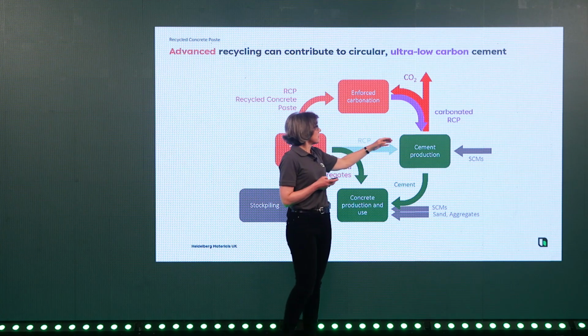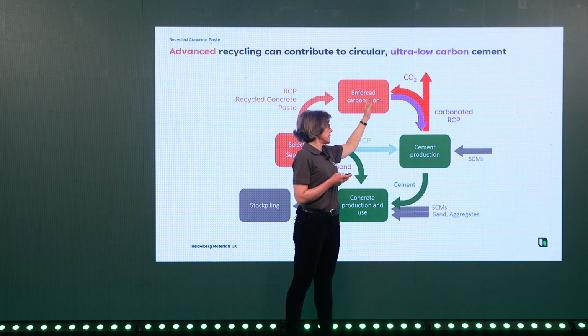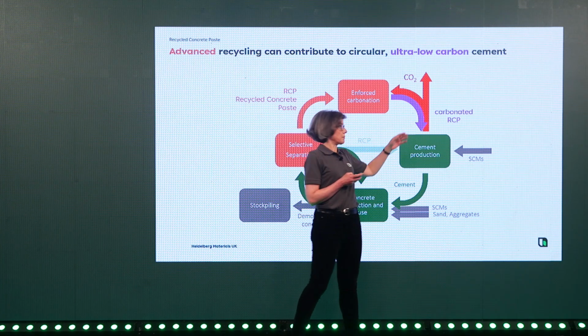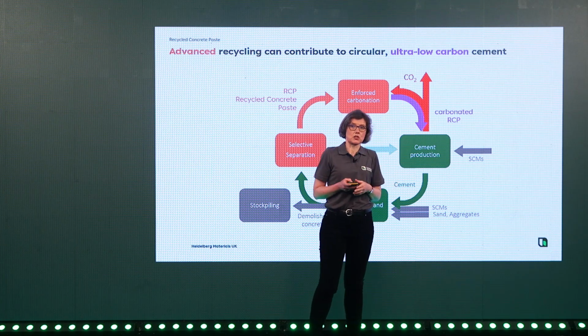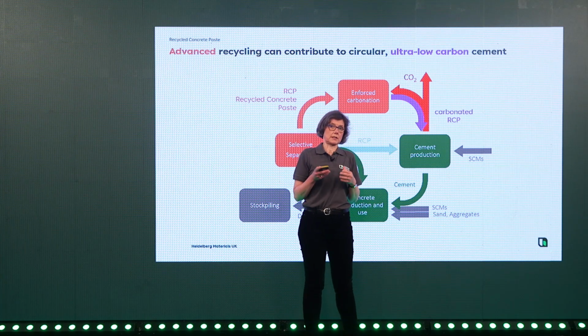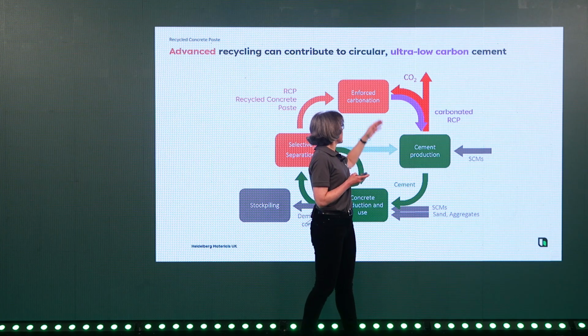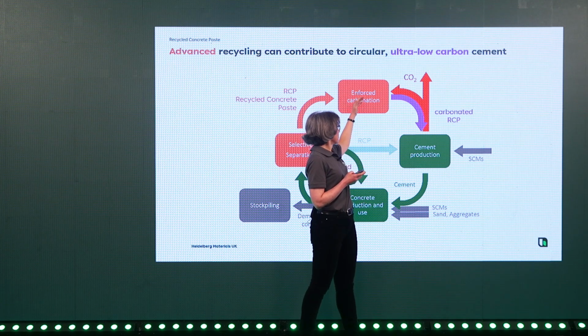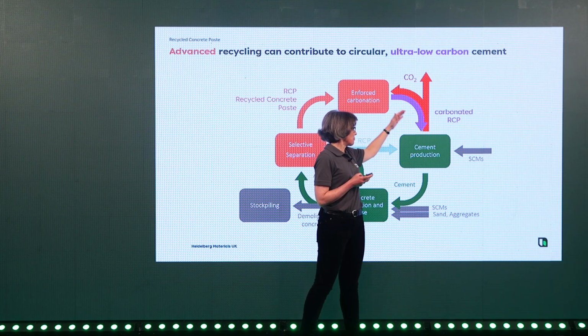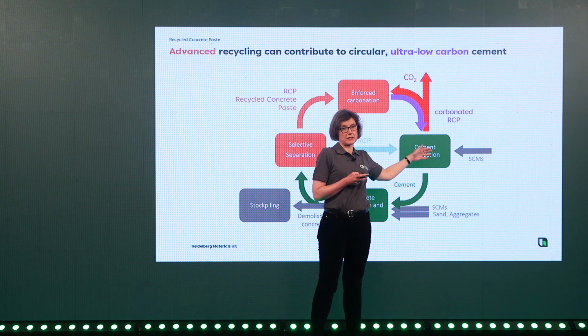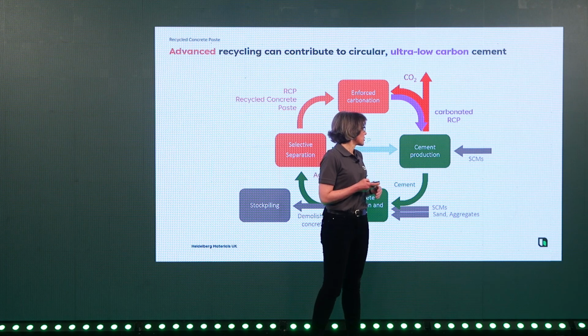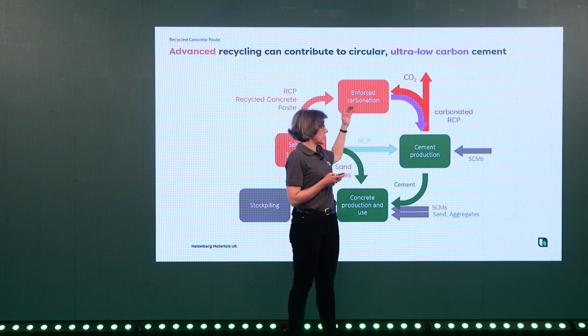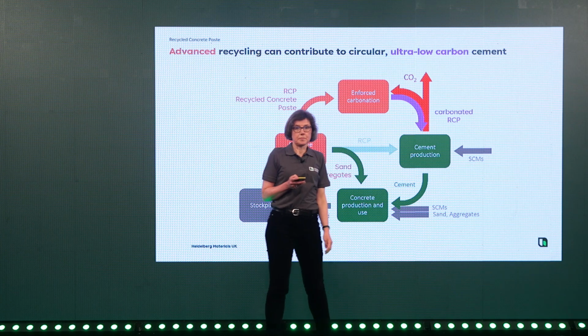This RCP we can actually carbonate with the emissions from our cement works, or really the emissions from any industrial process which has CO2 in its stream. And this carbonated concrete paste can then be used as an SCM, supplementary cementitious material, because it's actually activated. So we reuse material and we mineralize carbon.